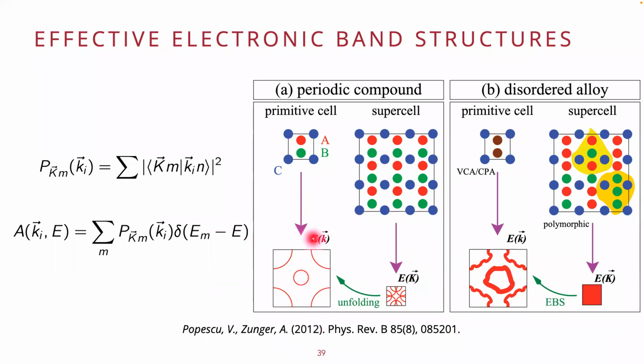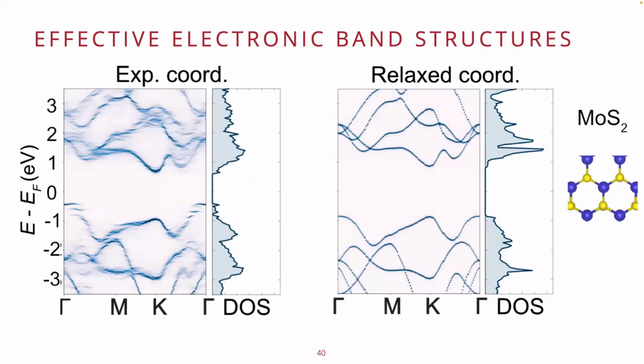In the same way, if you introduce any distortions or alloying, you can capture that information back so that we can compare our unit cell to our real system using different areas of our experimental coordinates, right? Then I'll show you an example here where we found an area that's just pure molybdenum disulfide with no defects in the same system. We can see that in regular 0 Kelvin ab initio methods, you would get exactly what you would expect, right? A nice semiconductor with a band gap.